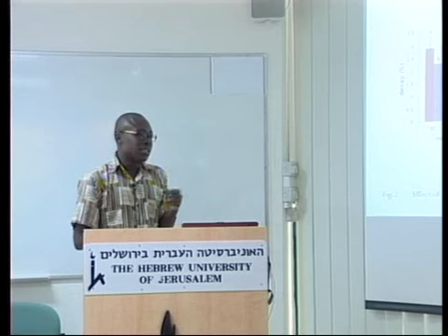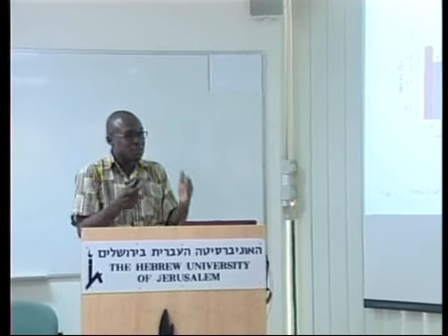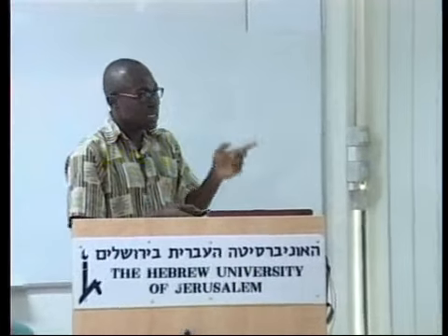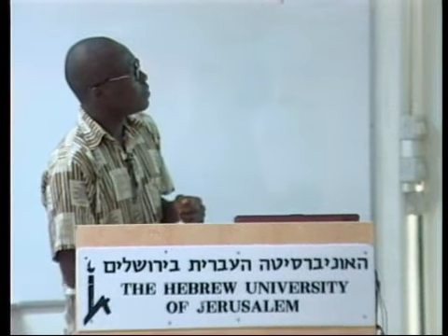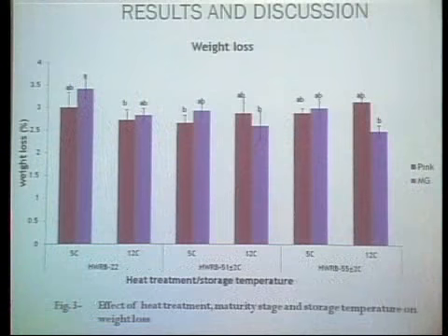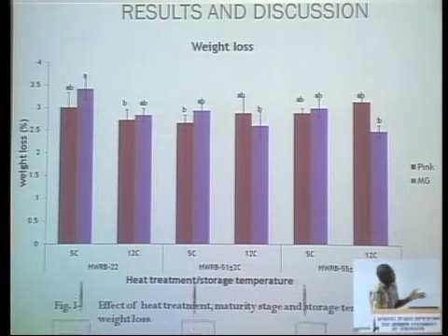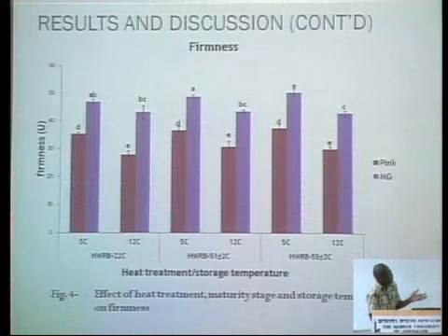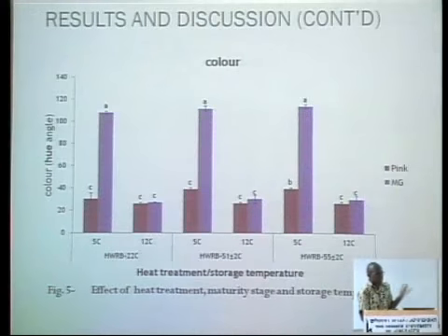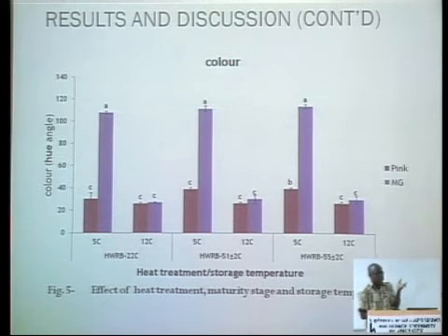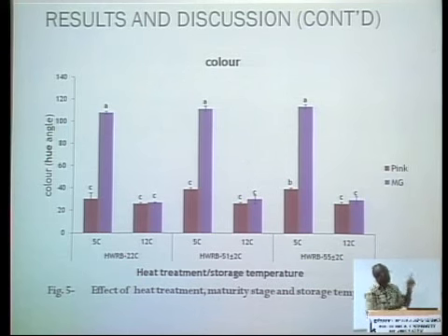22 is fine, but 51 and 55 is not convincing to use as a separate treatment. But it is convincing, because in the other parameters we noticed that there were no significant differences. But in the decay, and like I've shown here, there wasn't any significant difference in weight loss with the heat treatment. But if we look at the color, when we did the student t-test, we noticed that there was a significant difference between the heat treatments on color. And the inhibition was much higher at 55 than at 51.